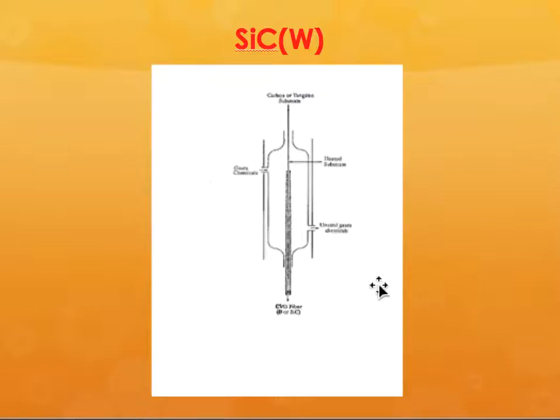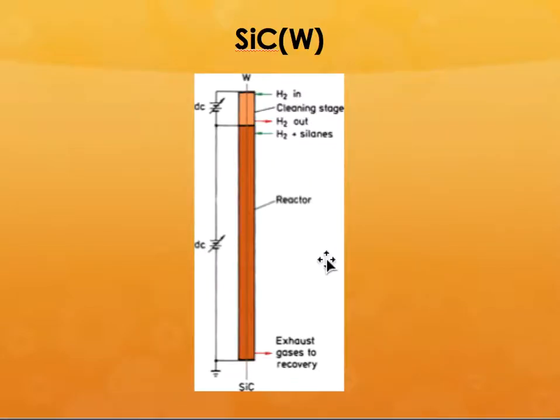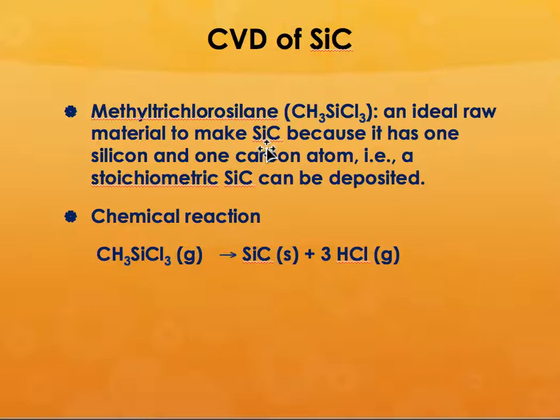So this is the schematic of the CVD process, where you are reacting it in a chamber, and while the fiber is being pulled through that, it deposits this silicon carbide matrix around the substrate. So as I said, it is methyltrichlorosilane, CH3SiCl3, and because it has one silicon and one carbon atom, you can get a stoichiometric ratio of silicon carbide, and it forms a byproduct of hydrogen chloride gas.